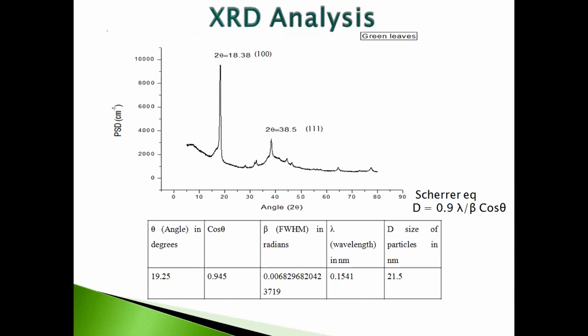Then the XRD analysis was done, and we received the characteristic silver nanoparticle peak at 38.5 degrees 2 theta, which signified the crystal structure of the silver nanoparticles that we made. And we also calculated their size using the Scherrer equation that is given in the PPT presentation, calculating the angle and the full width at half maxima. The size of the particle was about 21.5 nanometers. That was the calculation through the data that we received from XRD.